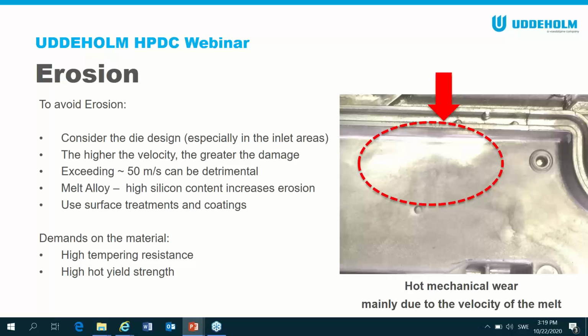And of course, the aluminum matters as well. It's high silicon, and that's obviously going to affect what's going on there with the washout. So you have to protect the tool steel with a coating or a surface treatment. So here you've got the choice of nitriding or obviously Eifeler do a very good coating called Tigral that is quite successful in lots of dies. But that coating and nitriding has to be able to stay on the material. So you still need a material underneath it, which has got very good high tempering resistance and hot yield strength. Because without that, the coating is not going to stay there.